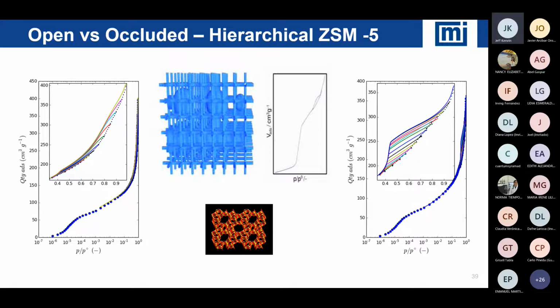So the material on the left, that set of material, the hierarchical pores, the mesopores and macropores that were introduced were created by protecting the micropores. So it's a demetallation process, some steaming and some treatment with a basic material to etch away the alumina with the acid and steaming, and then the silica with the basic material to introduce mesoporosity. Notice by one set of treatments, we get a very narrow hysteresis loop on the left. By a different set of treatments, we get a very broad hysteresis loop on the right side.